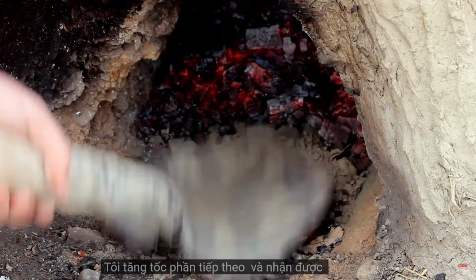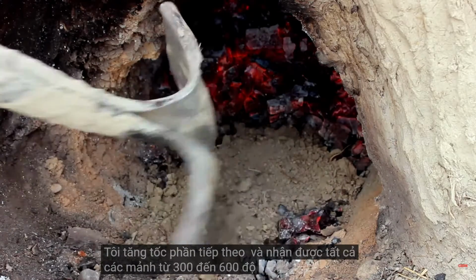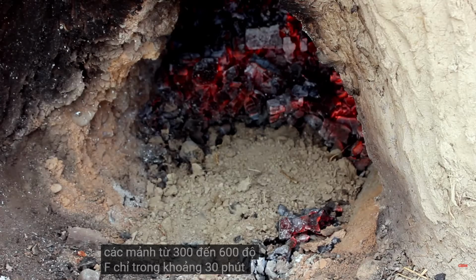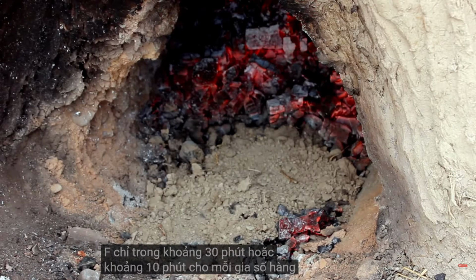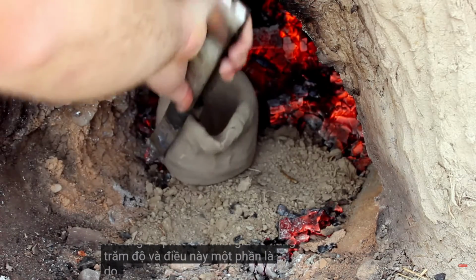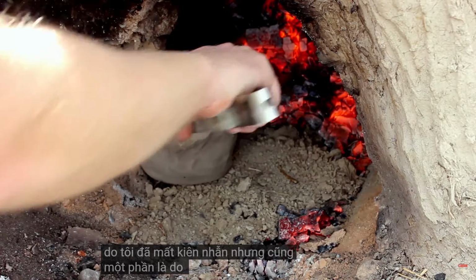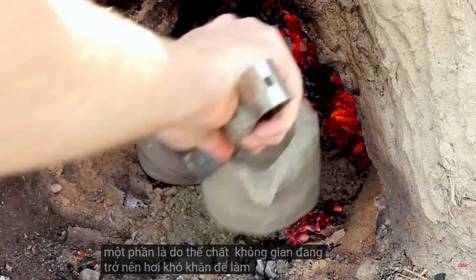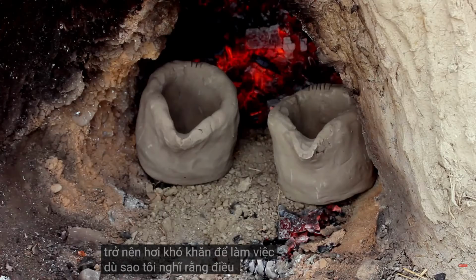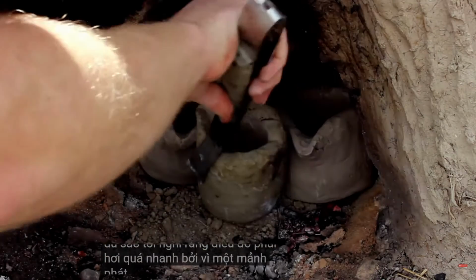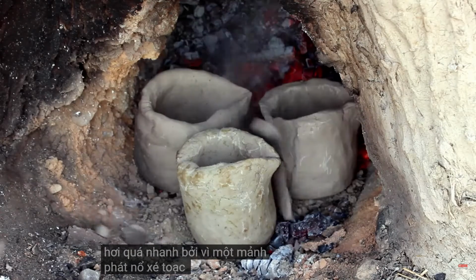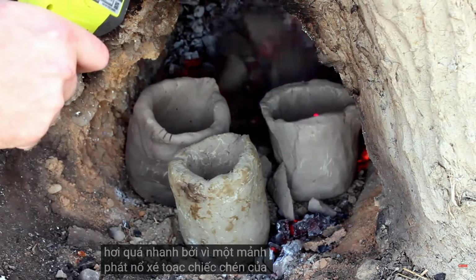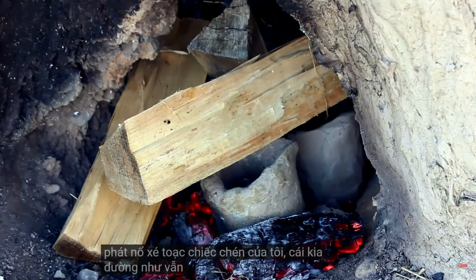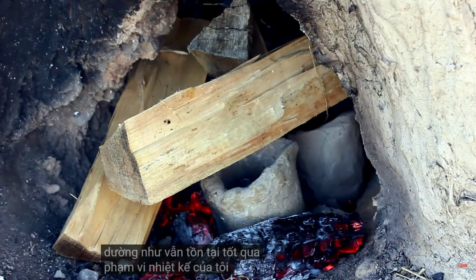I sped up the next section and got all the pieces from 300 to 600 degrees Fahrenheit in only about 30 minutes, or about 10 minutes for every 100 degree increment. And this was partially because I was getting impatient, but also partially because the physical space was getting a little difficult to work with. Anyway, I think that must have been a little too fast because one piece exploded. Rip my crucible. The other two seem to survive okay up well past the range of my thermometer, though.